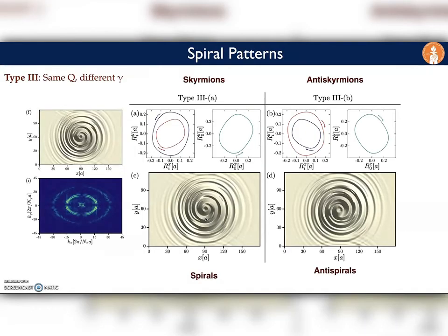the Skyrmion core. Turning now to bilayers consisting of textures with the same topological charge but different helicity, although the two particles will have the same gyrotropic mode, a Néel Skyrmion performs a larger circular path compared to a Bloch texture, while their charge separation distance follows this circular path with a sense of gyration that is determined by the topological charge. So spiral outwards traveling spin waves are created in Skyrmion bilayers, while anti-spirals in anti-Skyrmion layers.